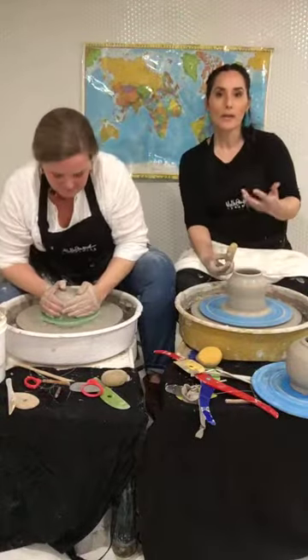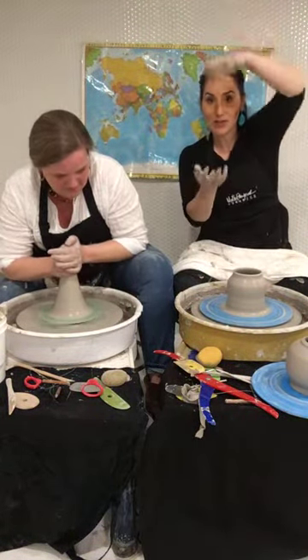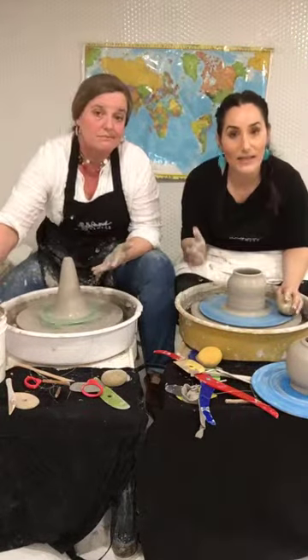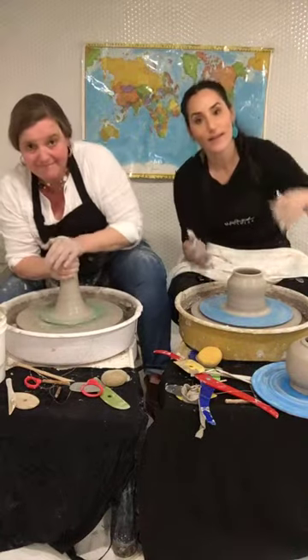We did one time have the kiln loaded with plate, stacked, stacked, stacked — and guess what? Every one of those plates shattered. We don't stack plates. You get like maybe foot to foot, lip to lip. That's it. New layer.